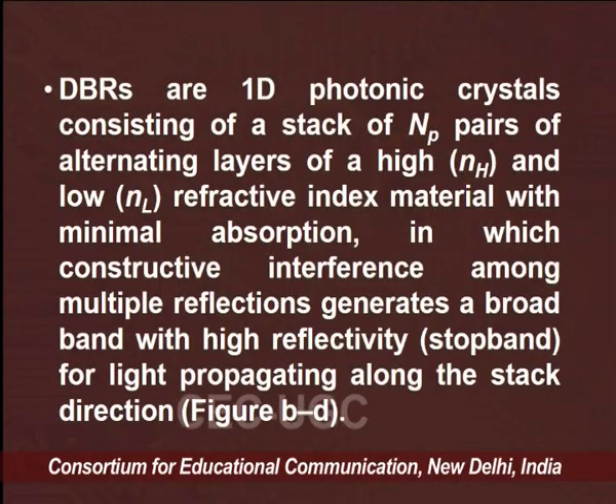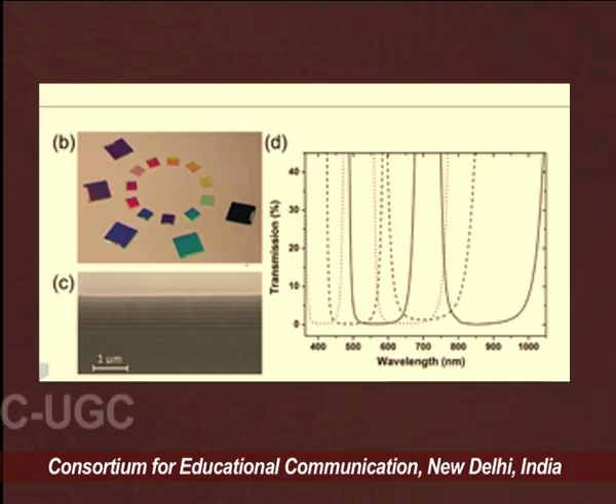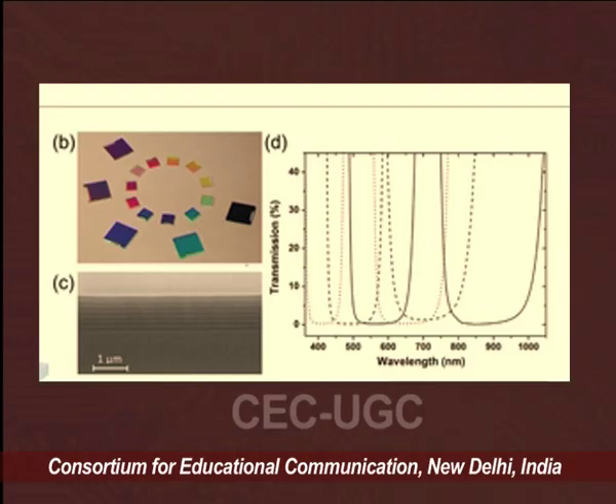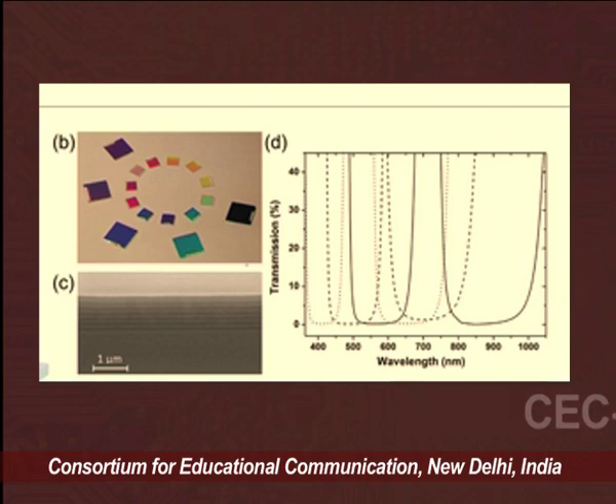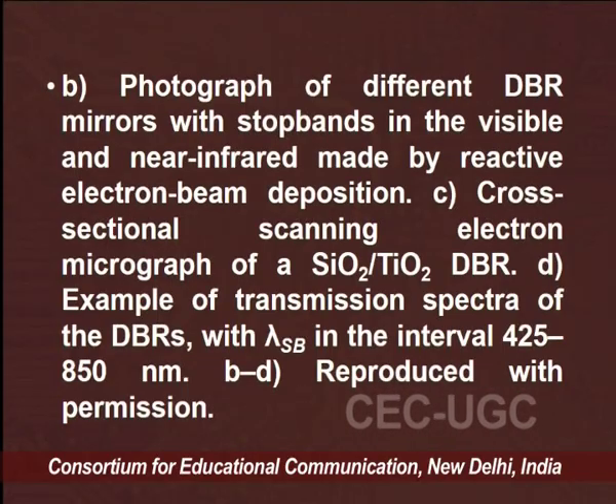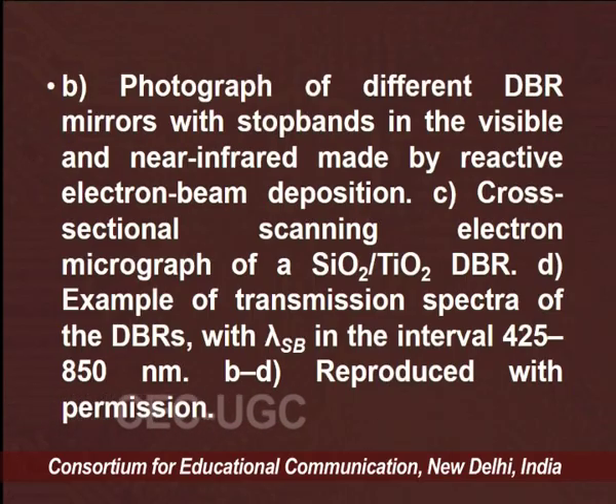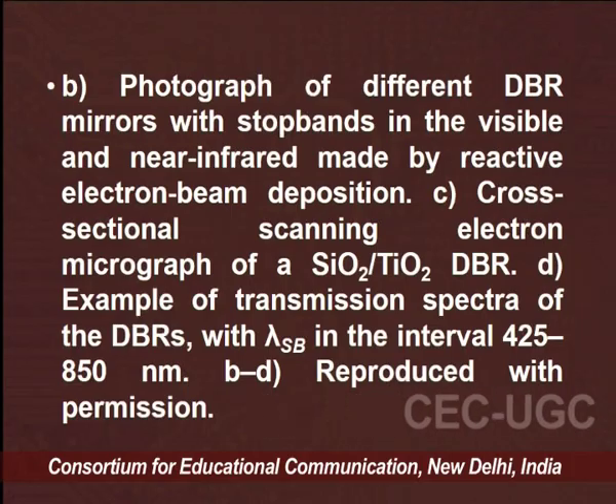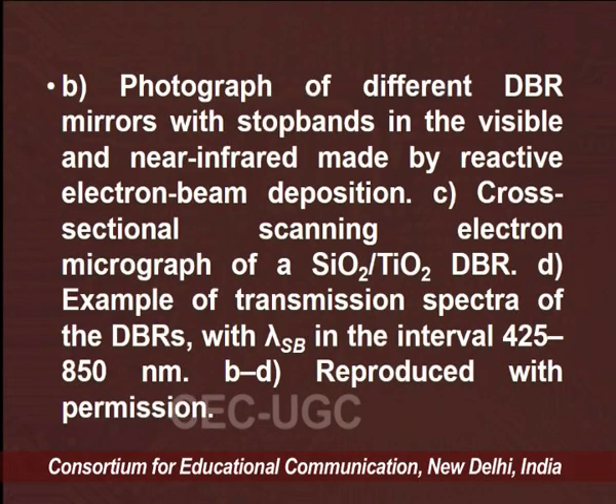So, the light is propagating in the various stacks that you can see on the screen, and when it propagates in the stacks, we can have this type of band here. So, that is a photonic crystal. This photograph shows different DBR mirrors with stop bands in the visible and near infrared, made by reactive electron beam deposition. This is the cross-sectional scanning electron micrograph of SiO2 or TiO2 DBR, and the transmission spectra of the DBR with lambda SB in the interval of 425 to 850 nanometer.